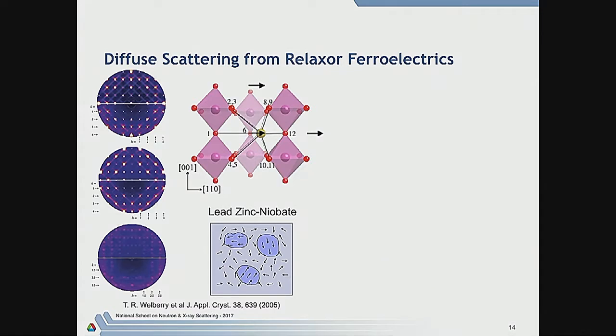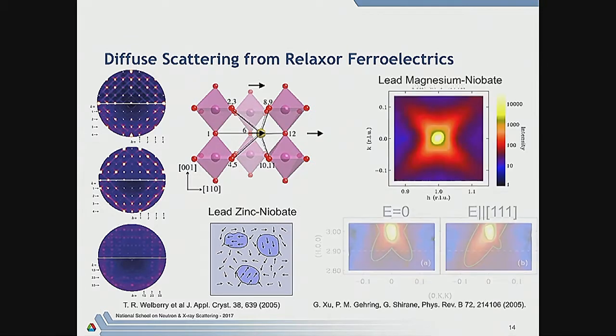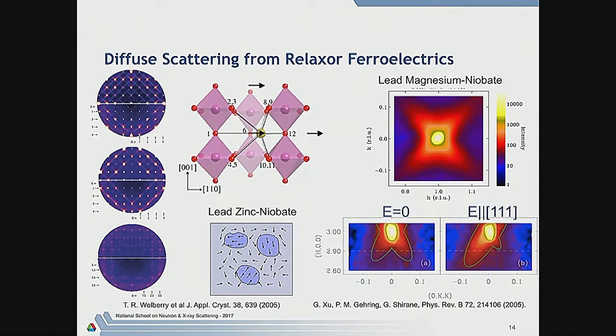And so diffuse scattering has been used a lot to measure this material and try to understand whether, for instance, it's appropriate to think of this in terms of these nanodomains where you have basically ferroelectric order but only over a very small region in space that are somehow frustrated in this lattice, or whether what people now believe is it's more likely to be a kind of random field system, if you know anything about that kind of statistical physics. But again, you get beautiful diffuse scattering from this, which has been analyzed in terms of all these models.